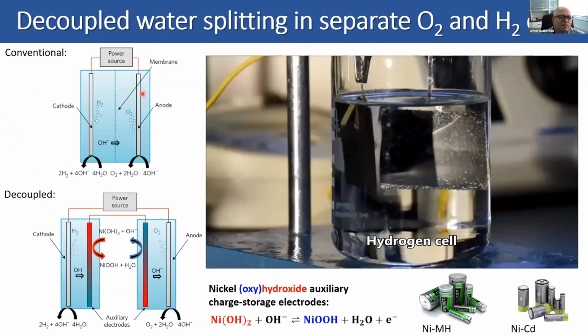So if this is the scheme of the conventional electrolyzer, again, cathode producing hydrogen, anode producing oxygen, and a membrane to separate them, we divide the cell into 2 compartments. So one compartment, or now it becomes one individual cell, produces only hydrogen. The other one produces only oxygen. And you can separate them over many meters if you wish, because they are connected only by electrical cables. The point is you need to make a way for the ions, in this case hydroxide ion, to transfer from the cathode to the anode. Otherwise, you will not complete the reaction.